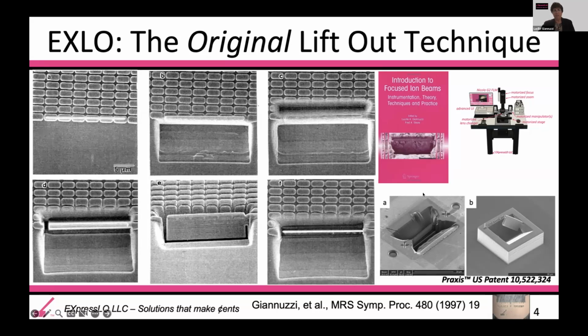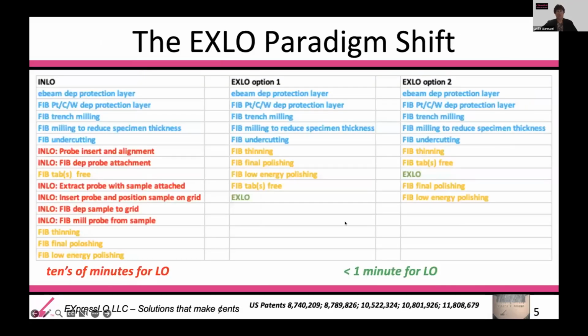But the idea is to prepare a FIB specimen such that it is retained inside of the trenches, and then you move the sample outside of the FIB onto a standalone micromanipulator station with an optical microscope so that you can see where the specimens are and how to then pluck them out. So the paradigm shift is basically, at what point do you do lift out?